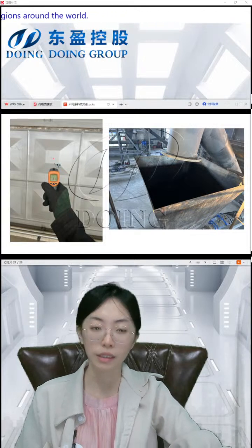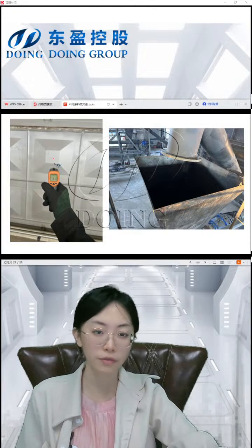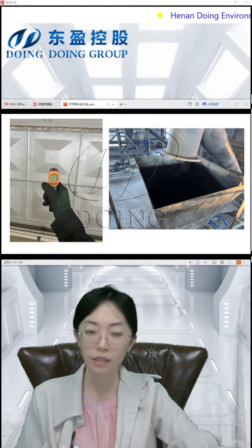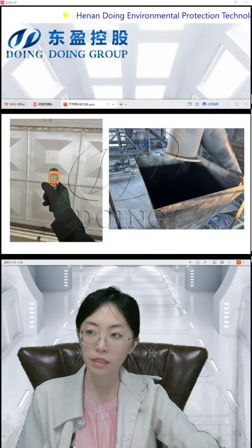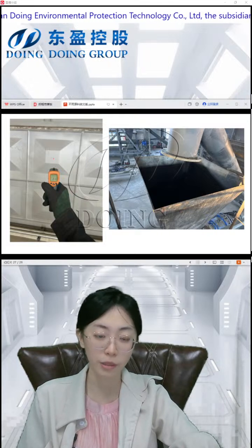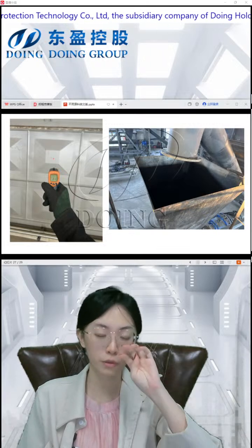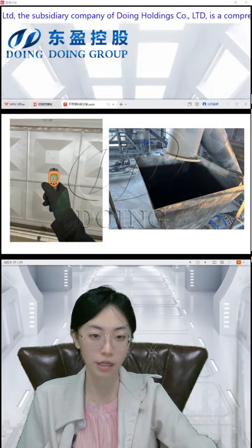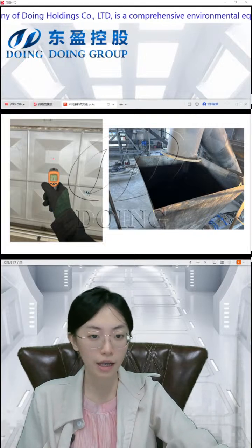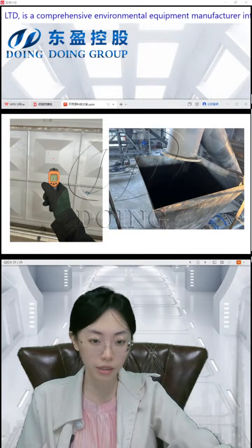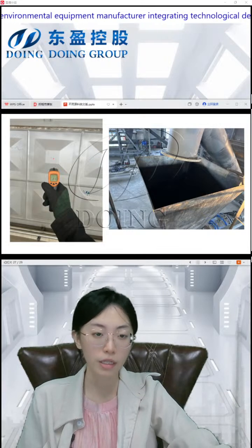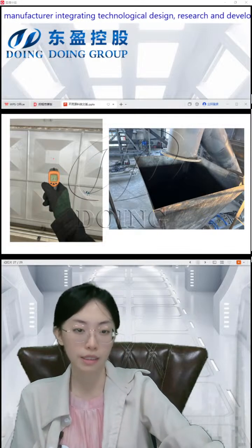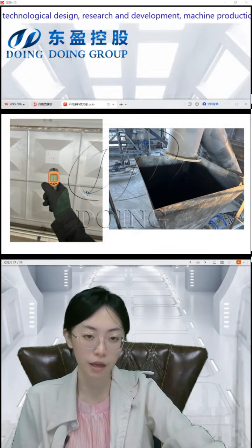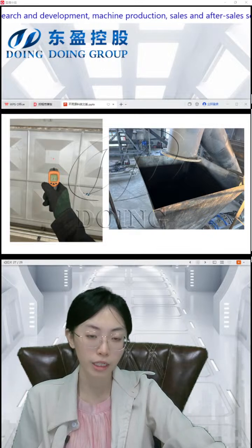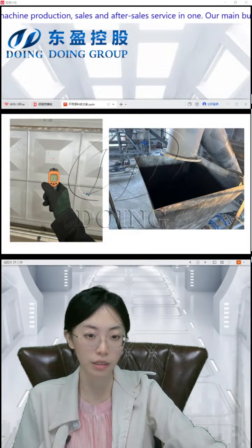And this is the installation cover that we have for the fully continuous plant. Here you can see the temperature is 31 degrees during production, so it's very safe for workers to touch the installation cover. The temperature inside is 400, but the outside is lower than 35. So we have 6 layers for the fully continuous pyrolysis plant to protect the temperature and to prevent the release of smoke gas.